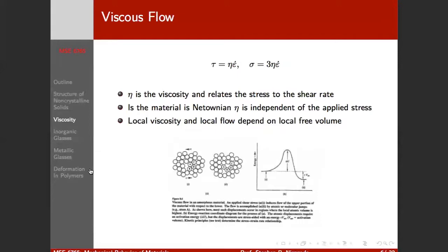Right? And this allows this cluster to accommodate this shear and gives us small free volume changes elsewhere in our material, right? And because this involves a diffusion-like jump here, that means we have an activation energy, right?